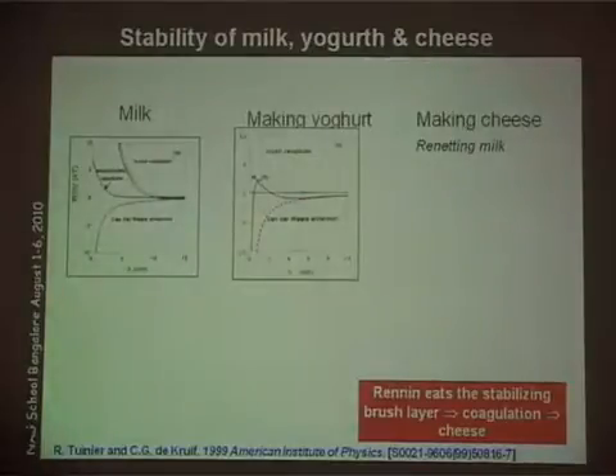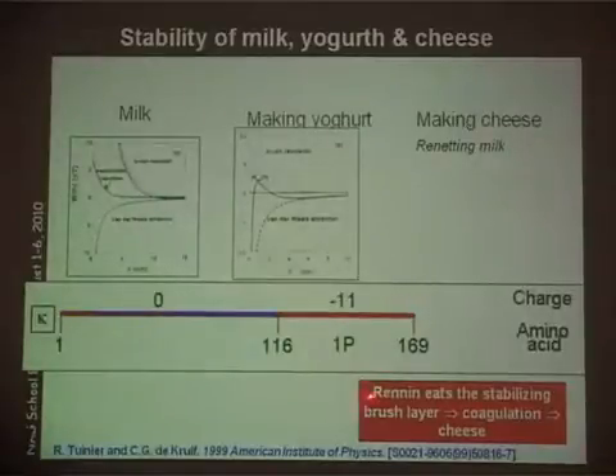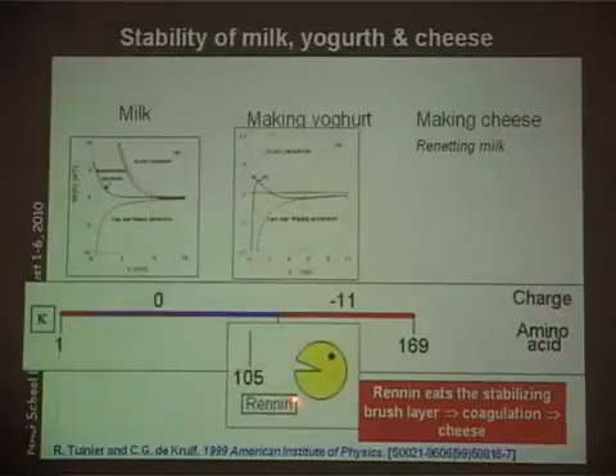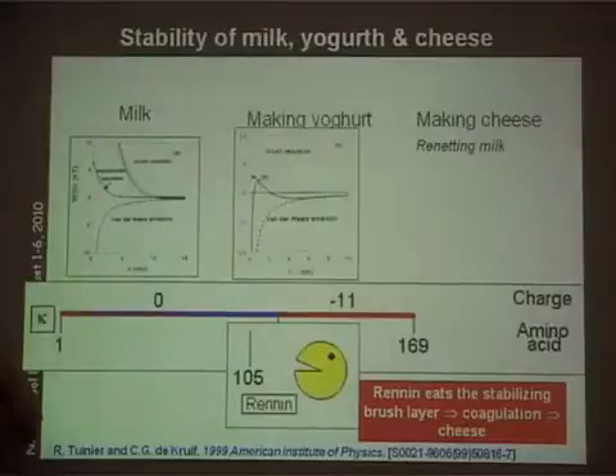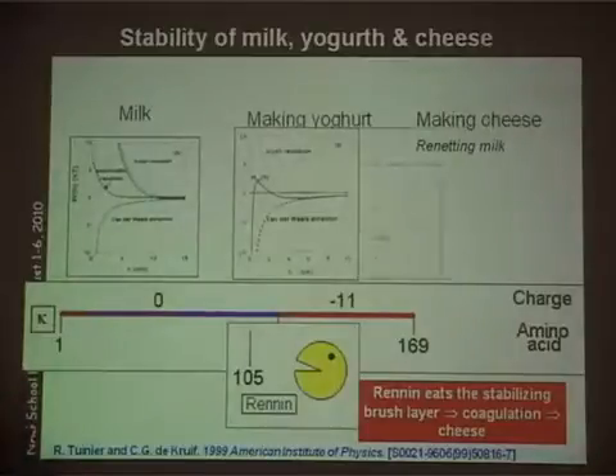Now, when you make cheese, and that's very clever, you add something called rennin, a little enzyme that basically cleaves off the kappa casein at this point, and that goes into solution, and the rest stays in the micelle. So what you have done is you just shave off your stabilizing, negatively charged brush, you're left with some hydrophobic core, and that's what you then get.